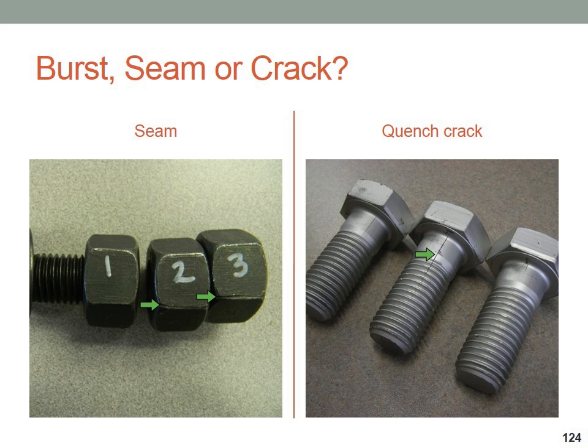We actually have started to see more of them in recent years as A490s are starting to get coated. This particular example is an A490 that was coated. I don't know that this crack would have been identified visually by anybody on a black fastener, but since it was coated, it happened to get caught by our QC people here on receipt inspection, and ended up having to basically segregate and scrap that entire lot. They happen as a result of a severe quench, often of a high hardness alloy material. And again, there are no doubt thousands, if not hundreds of thousands of bolts with quench cracks in them in structures around the country, but typically not in high enough quantities to affect a particular project or another.